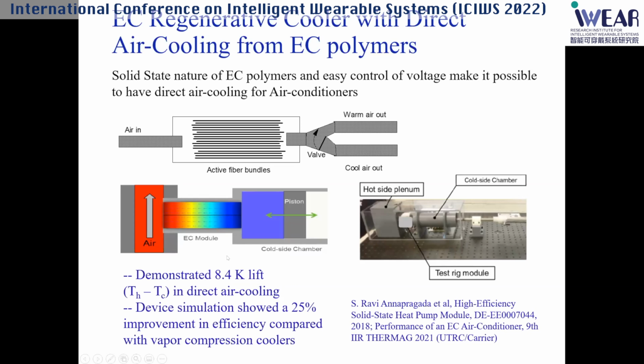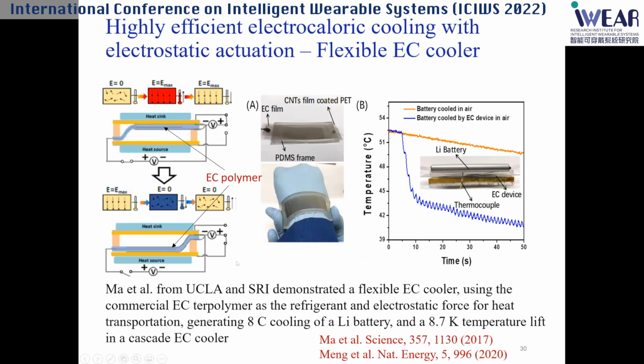But still the temperature lift isn't that great. Also, a team from UCLA and SRI developed a kind of flexible EC cooling device, which they published in Science. Basically, this is the EC polymer film - when it becomes cold, it goes to the cold side; when it becomes hot, it goes to the hot side to eject heat; and when it becomes cold again, it goes to the cold side to absorb heat. Basically, in this way, you pump heat between cold and hot ends. They demonstrated about 8 degrees cooling of a lithium-ion battery, and also demonstrated an 8.7 Kelvin temperature lift in a cascade EC cooling setup.